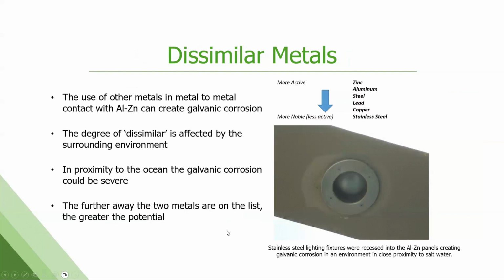Dissimilar metals, let's dig in a little bit more. This is a stainless steel canister recessed through a painted galvalume overhang. So again, more active, less active. The further away these metals are from each other and in a corrosive environment, the more likely you're going to have this phenomenon. So the metal is corroding underneath the paint. That causes the paint to lose adherence and it bubbles off. This comes in as my paint is failing claim. It's not the paint, it's galvanic corrosion.